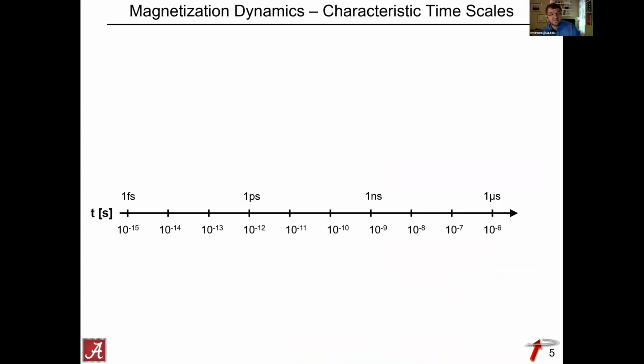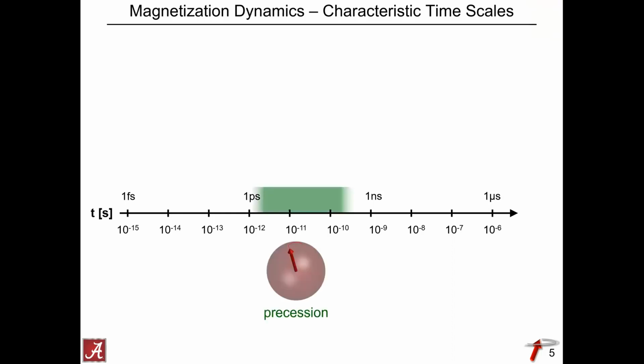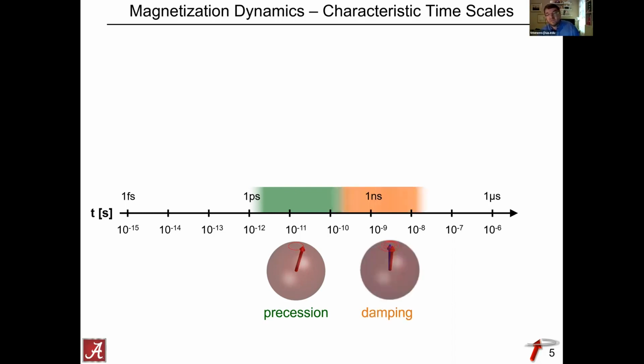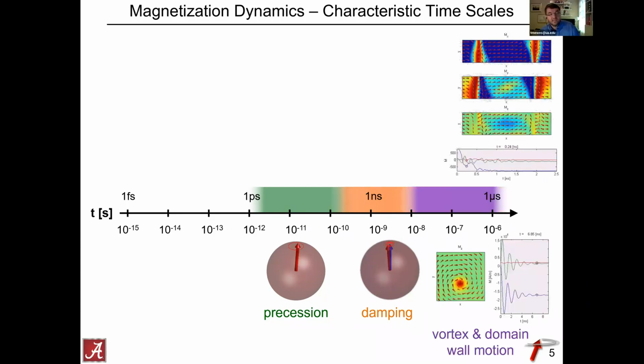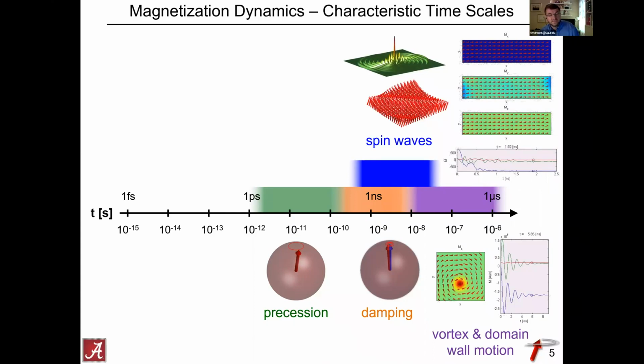And the numbers here are just typical values. There are obviously a lot of parameters that you can play with to change that, but the precessional dynamics, so a full precession, happens in a fraction of a nanosecond, whereas the damping typically happens on the time scale of nanoseconds. When you then look at more complex dynamics like vortex and domain wall motions, those all typically happen at much longer time scales, which is shown here schematically for a couple of examples. You also have spin waves that cover a similar time scale.